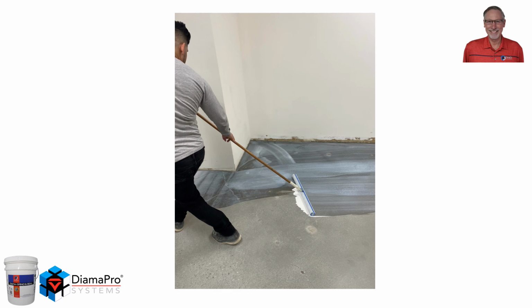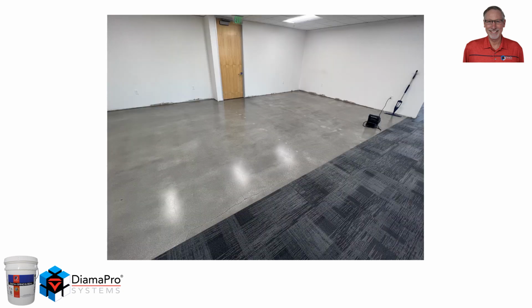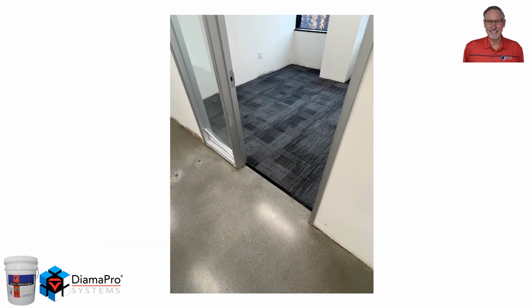If your final film contains that white haze to it, that means the material is applied too heavily or the temperatures are too cool and the humidity is too high. Here's the cured system. The white haze is gone and no streaking is visible. The concrete is slightly darker than original, but yet you retain the natural appearance of the ground slab itself.